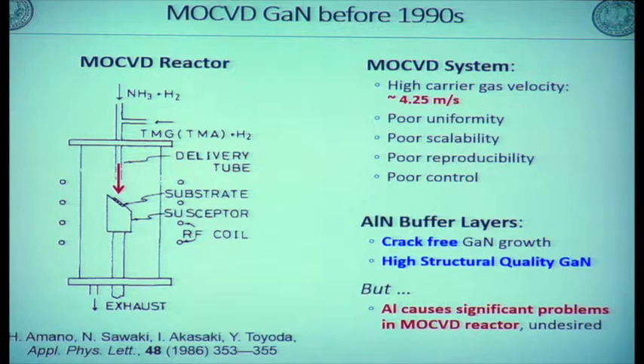Initially, I had to grow gallium nitride crystal. The method is only MOCVD, so we had to use MOCVD for gallium nitride crystal growth. Another Nobel laureate, Professor Akasaki, and Amano were already working on gallium nitride crystal growth. This is their MOCVD reactor. They were working at Nagoya University. They used this MOCVD, but this MOCVD had a lot of problems.